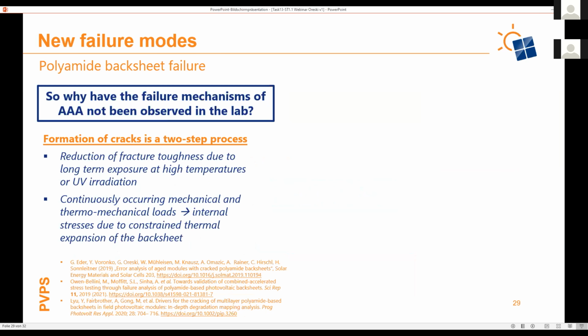Because this crack formation is a two-step process. First, we have some sort of reduction of the fracture toughness due to long-term exposure at high temperatures and UV radiation. And then we have continuously mechanical and thermomechanical loads on the PV module - think of the daily temperature changes causing stresses because of the different thermal expansion behavior.